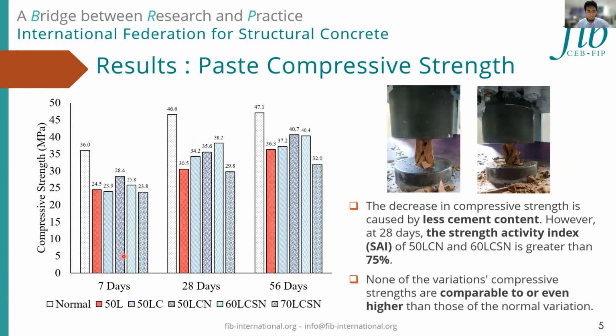This is the first result of my study. In terms of the base compressive strength, it is known that replacing cement with limestone results in a decrease in compressive strength. You can see it in here from normal variation to 50L, which is obviously caused by a decrease in cement content. The use of calcium carbonate, GGBFS, and natrium hydroxide solution showed a good trend in that it could increase the compressive strength. We can see it in 28 days base compressive strength from 50L to 60 LCSN.